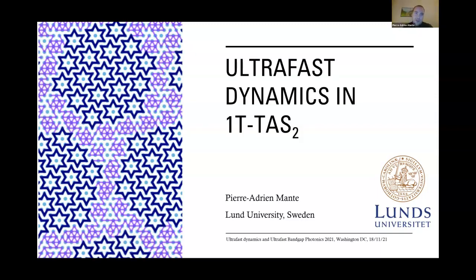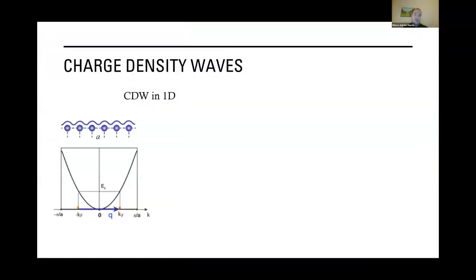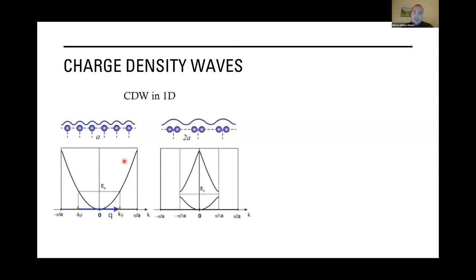And tantalum disulfide, to understand its physics, the main phenomenon that rules the physics of this material is charge density waves. So charge density waves, the best way to understand them is to consider a one-dimensional metal. And so in a one-dimensional metal at low temperature, electrons are going to fill the parabolic band until the Fermi level. And this state of matter is in fact not the most energetically favorable state. The formation of a periodicity with a wave vector corresponding to the Fermi surface will lead to the bandgap opening, which is going to reduce the energy of the electronic structure. And this reduction in the electronic structure energy is often more advantageous than the cost of reorganizing the lattice.